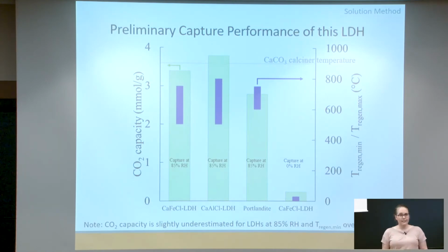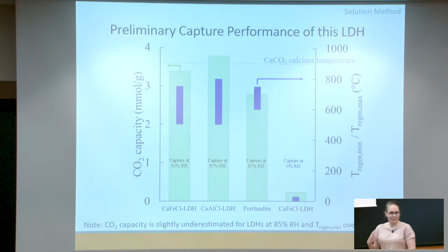So here are some capacity results. What's shown in green is the amount of CO2 that was sorbed to the material during capture, and we're between about 3 and 4 millimoles of CO2 for our 2 LDHs. We also did Portlandite, that calcium hydroxide, and that has a lower capacity for these conditions compared to the layered double hydroxides. But if you do sorption at 0% relative humidity, you can see how much of an impact dropping the relative humidity has on the capture capacity. So we really want to look at in between these relative humidities. And then looking at the temperature required for regeneration, these bars give you an idea of the temperature range at which the CO2 was lost from the material when you heated it up.